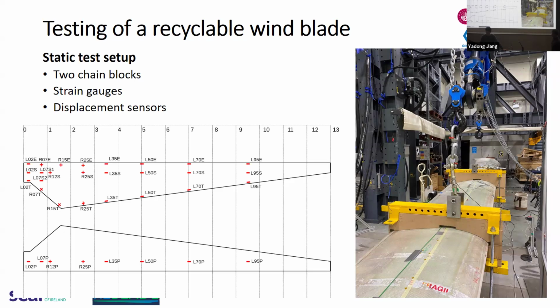It's different from the previous demonstrator test. Here we didn't use the actuator because it's a 30-meter long blade and it's quite flexible, and the stroke length of the actuator is not long enough for this deflection. So here we used 2 chain blocks to apply the loading, and between the chain block and the load points there is a load cell to measure the load. And these clamps are manufactured using MDF and CNC'd to ensure that they match well with the blade surfaces.